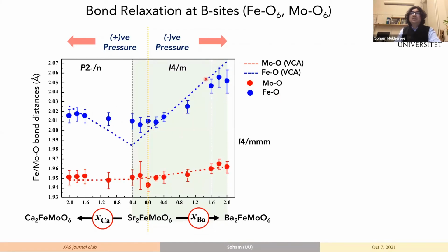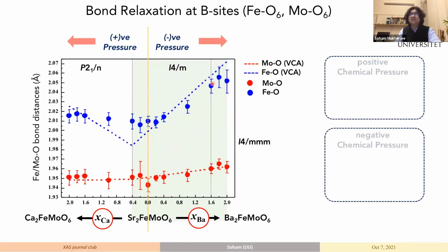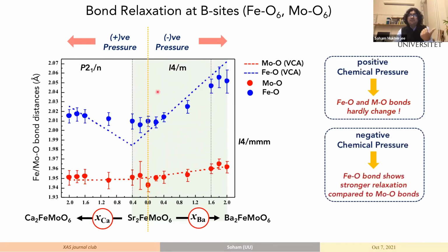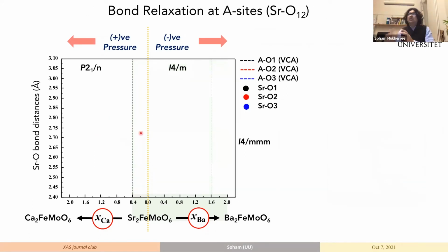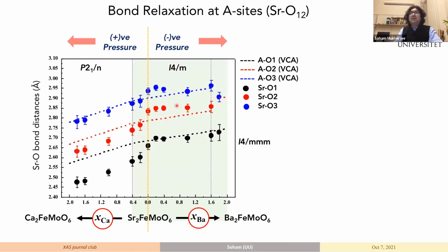And we can see immediately that for the barium side, there's a stronger relaxation of the distances, whereas for the positive pressure side, the Fe-O and Mo-O bond distances hardly change. Now, we look at the A site, and there is a cuboctahedra that you have in SrO12. So right now I'm showing only the strontium-oxygen distances, and there are three different distances which define the cuboctahedra in the system. When we look at this, this is what we get.